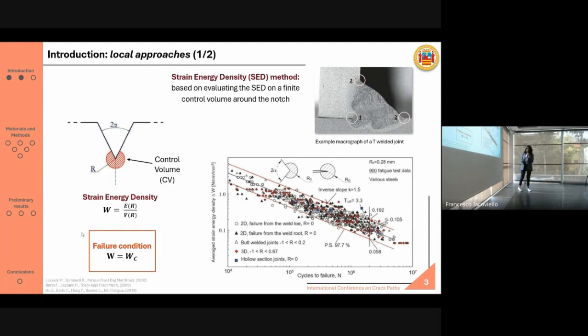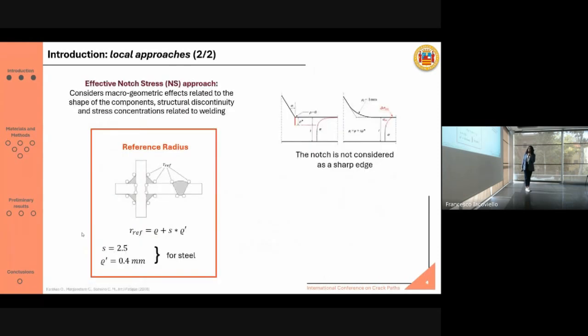And here we have the fatigue strain energy density versus number of cycles to failure. And what we notice is that there is a clear scatter band that is able to comprise most of the experimental results. Concerning the other approach, effective notch stress, this considers the macrogeometric effects which are related basically to the shape of components and the structural discontinuities that are related to the welding bead.